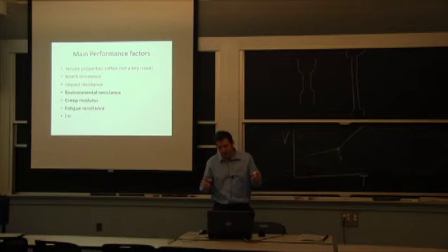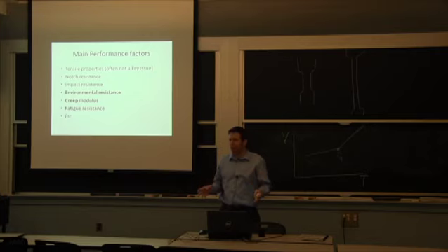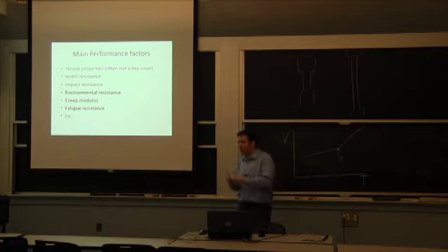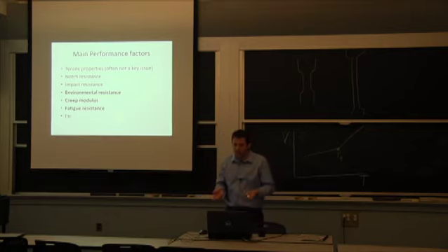As far as notch resistance and impact resistance, what I'd like you to think about is it's very much molecular weight dependent. Because if I make a notch or an impact, I need to spread into that whole network of macromolecules. And the longer the chains are, you can't break the chains very easily. So they'll try to move one way or the other. The bigger they are, the harder it is to separate them. And that's why all the fracture type of properties go up with molecular weight. On the other hand, for the short-term properties, because of the crystallites, it's harder to form that very tight crystallite when you have long macromolecules. They all go all over the place.